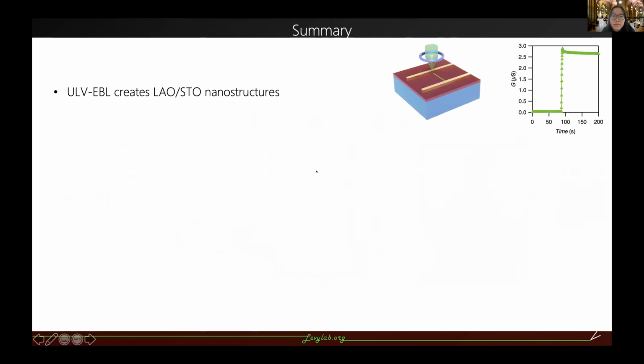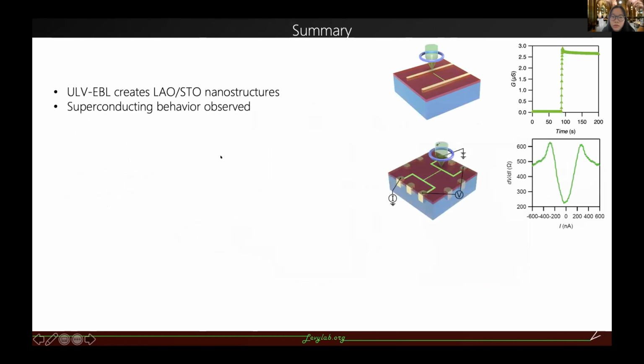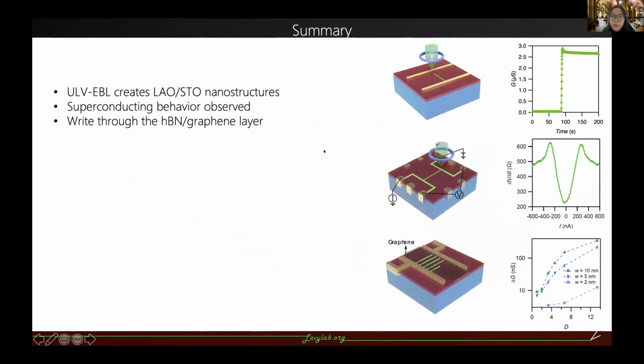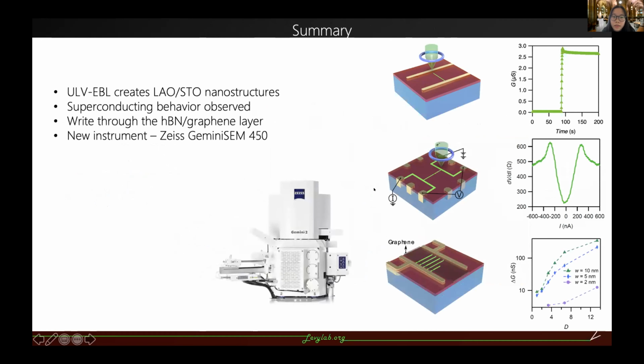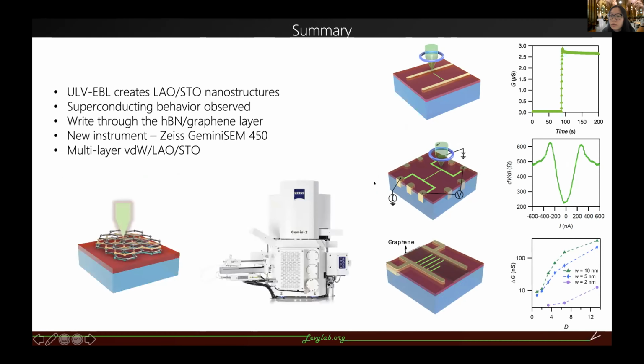And in summary, I showed that the ULV EBL can be used to create LAO/STO nanostructures, and it shows superconducting behavior. And we can even write through a thin layer on top, the boron nitride graphene and the graphene, and we have the new instrument. We're really looking forward to combining these methods with other multi-layer van der Waals materials, such as doing dynamic gating of the graphene using the LAO/STO nanostructures underneath the graphene, these kinds of interesting experiments later on. And that's all. Thank you.